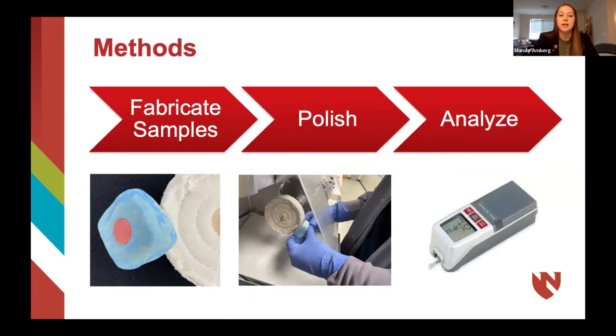For our experiment, we made 10 identical cylindrical samples from the different printers, and the lab fabricated 10 conventional samples. They were then placed in a putty jig. 5 samples of each category type were polished using either the polish or pumice system with a rag wheel until a clinically visible surface polish was reached and a polishing time was recorded. For consistency, only one operator performed the polishing in a random order, while the second operator kept a record of each of the samples' polishing time.